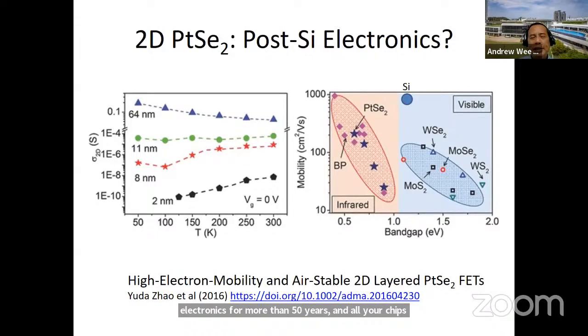And that's because silicon is easy to grow, and it has a good size band gap of about 1 eV plotted there, and a mobility of its carriers of about the order of 1,000 or more, okay, right here. And you see, we have not been able to find another material that could succeed silicon. Okay, another material with better properties.